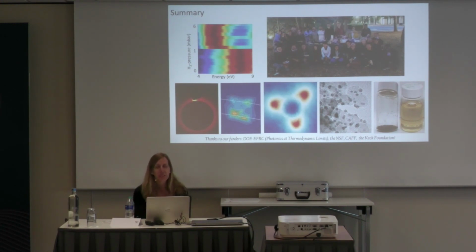Yeah. I guess the first thing is just doing accurate mapping of how much power is going to which part of the sample. I'd almost call that hotspot mapping. If you're doing light incoupling, just knowing where the light is hitting and making sure that's aligned with where your sample is, because these holders are a little bit finicky. So that's one thing to watch out for. Also just know that the amount of light that gets coupled into the fiber and then subsequently onto your sample is just a small fraction of what you put in. So don't buy just a 1 milliwatt laser and hope that you'll be getting milliwatts at your sample. You'll usually be getting much less.